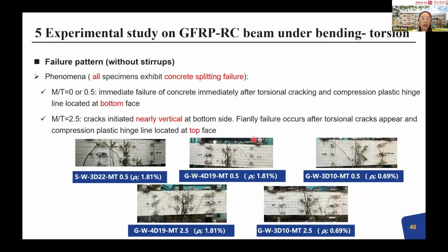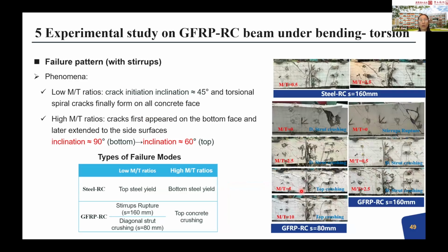And for the failure pattern, we also find that the cracking phenomenon is significantly different with the change of moment torsion ratio. For pure torsion, it is actually a constant diagonal cracking, and when the moment increases, you will see that the initiation is from the bottom, and then going up in inclined cracking. And also the plastic hinge line or zone for lower moment torsion ratio is at the long side surfaces. When the moment ratio increases, the compression zone comes to the top, which is also similar to our theoretical analysis.